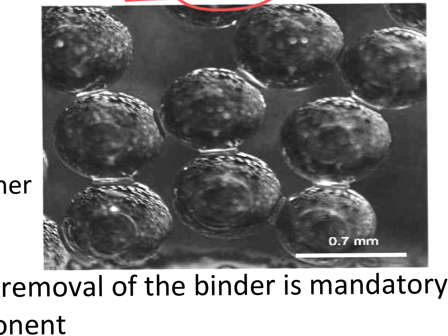You've got these nice, first off, round points of contact with the glass slide. Those are all capillary forces making pendular bridges and holding these beads very tightly to the glass that we're looking at. And you also have the same type of pendular bonds between the glass particles themselves, holding everything together.